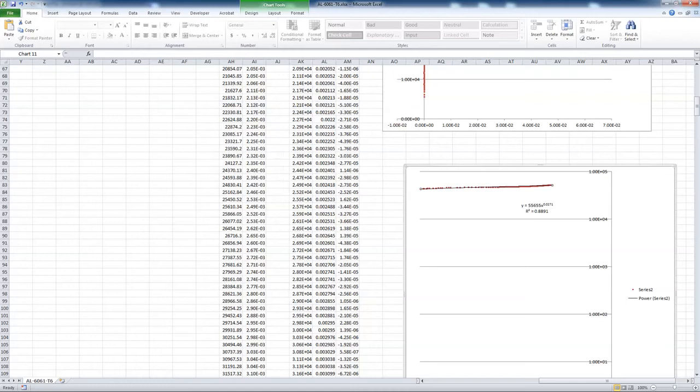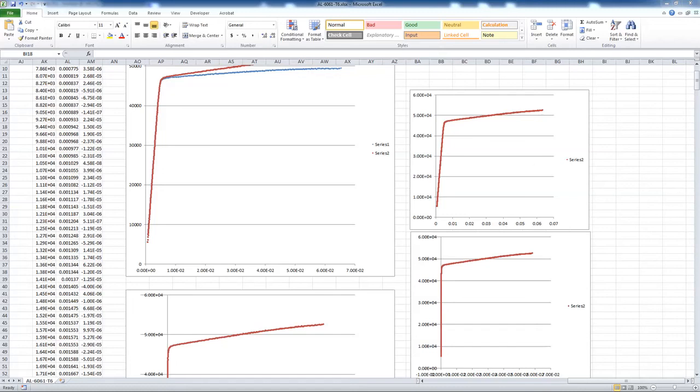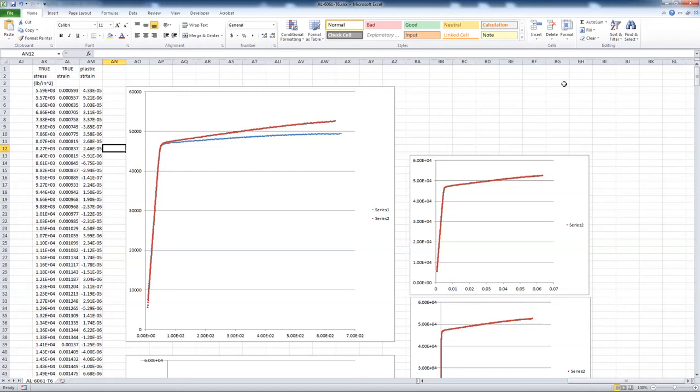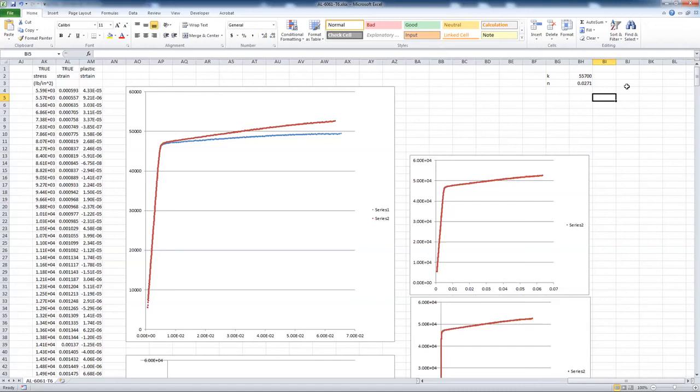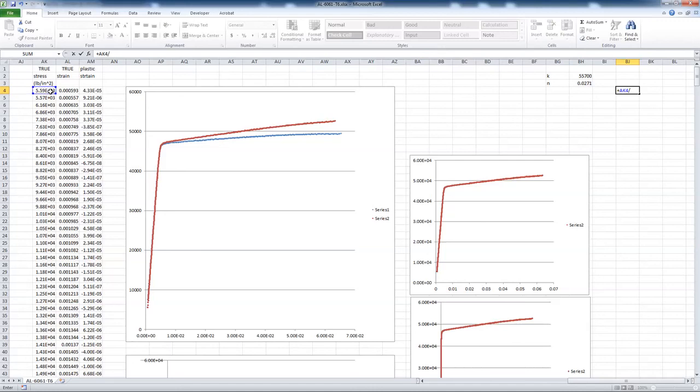Like I said, we're going to start with these coefficients as a starting point and we may have to adapt them. An n equal to 0.027 is kind of a small value for n, but let's work with this and let's see what we can get by plotting our fit as compared to our original data. Alright, so what I've got right now is I have my data, this is my experimental data for true stress and strain. And, now I'm going to start with my stresses. Here's my stresses and I'm going to use my calculated k and n and see what kind of comparison I come up with on my true stress and strain. So here will be my k and here will be my n. According to my fit, it was about 33,700. Now this is in units of psi and my exponent was about 0.0271.